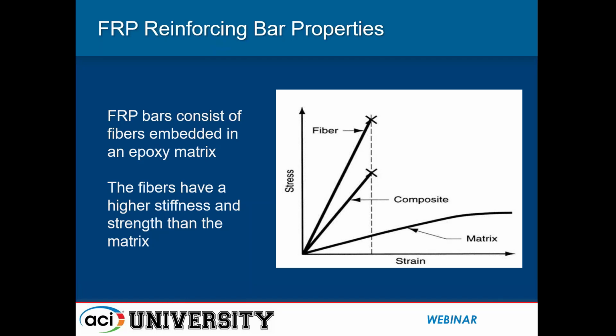When we combine the fibers with a matrix, the matrix is also approximately linear elastic. We see some plasticity towards the end of the stress-strain diagram. When we combine the fiber and the matrix, we form the composite GFRP reinforcing bar, and that is a linear elastic response up until failure.